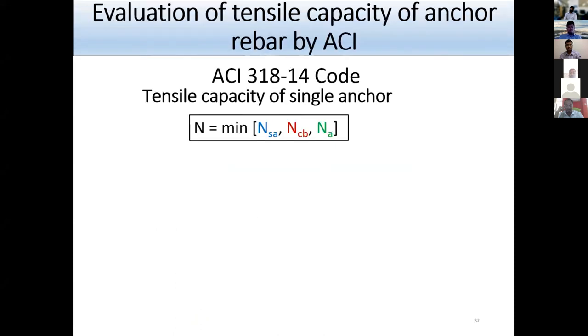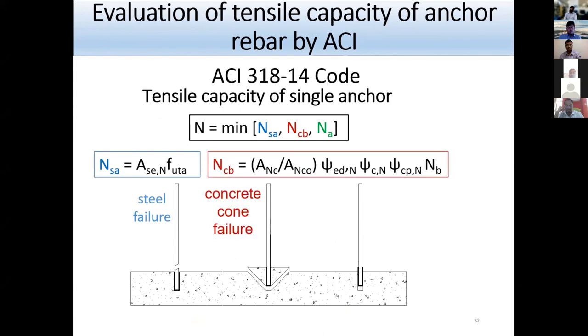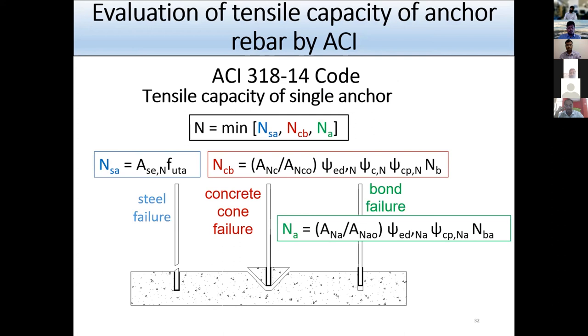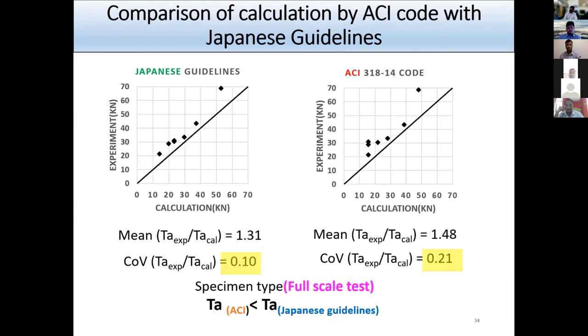Some may wonder why we focus on the Japanese standard rather than the American standard or ACI code. According to ACI code, the tensile capacity of a single anchor should be the smallest of NSA (steel failure), NCB (concrete cone failure), and NA (bond failure). We plotted the predicted values from both ACI and Japanese codes against experimental data, and for both scale and full-scale tests, we found that the ACI code predicted strength more conservatively than the Japanese standard.